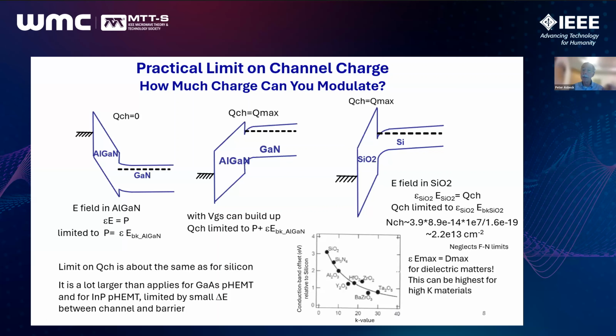It is limited by the breakdown field and dielectric constant of the SiO2 oxide that's typically used. And for that matter, it's really the D vector rather than the E vector. Right, so high-K dielectrics that have high epsilon can possibly reach higher levels of charge density that you can modulate usefully within FETs.